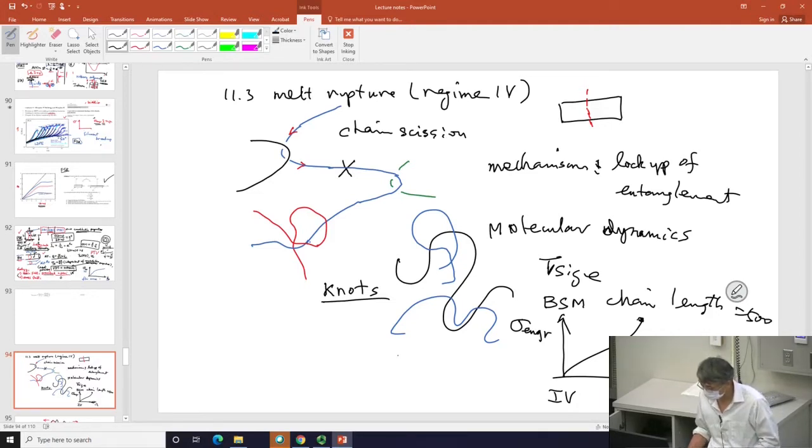So apparently, this rupture is related to the chains undergoing scission. At least some of the chains must have undergone scission. And as soon as it undergoes scission, it will unzip. The chains will start to lose their ability to hold up the network. So we were very intrigued by why this is possible in the absence of crosslinks.